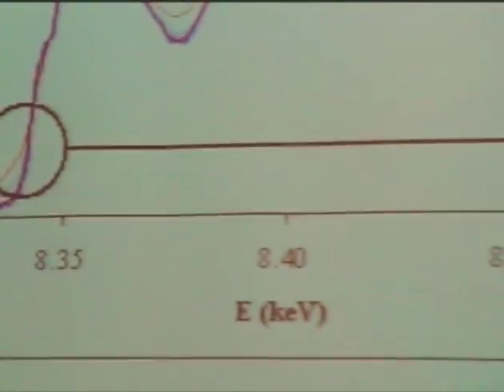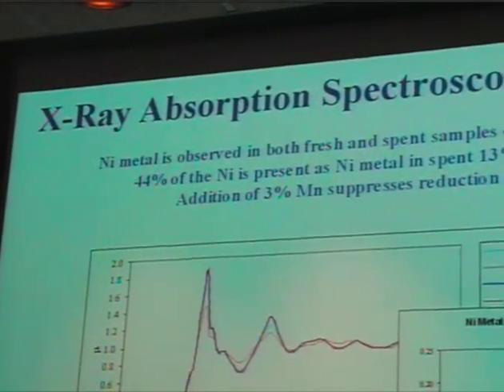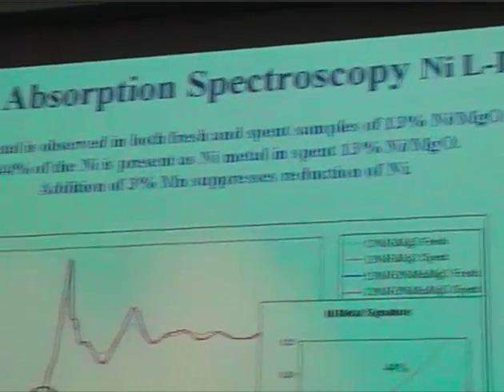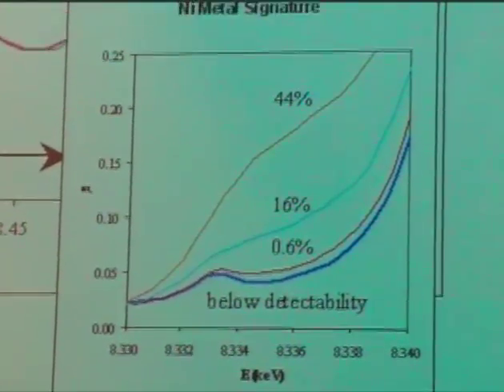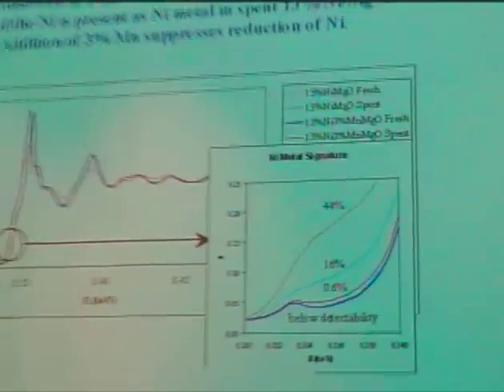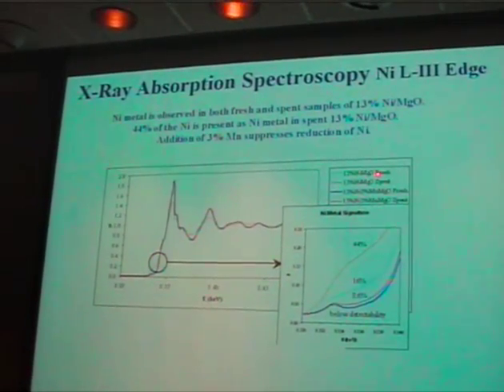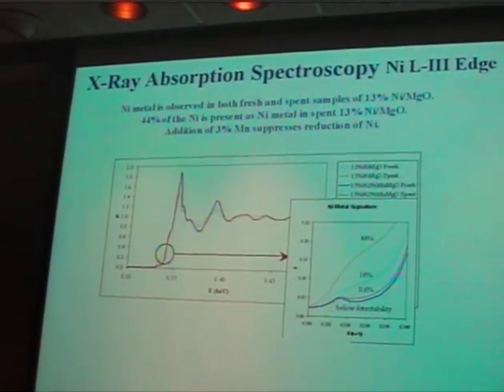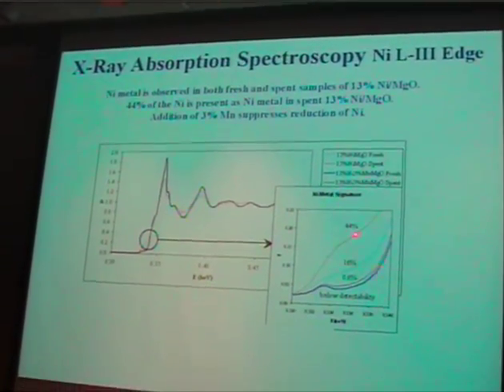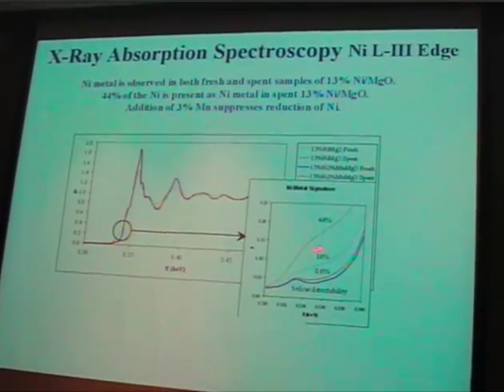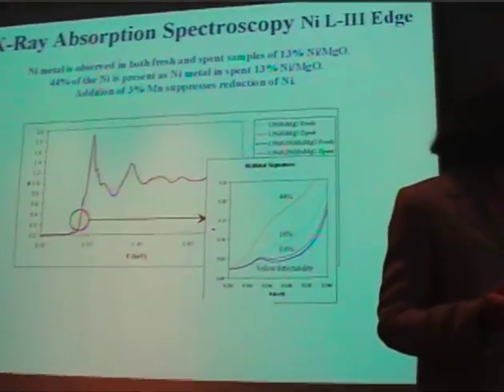So here you can see the blue line would be the fresh catalyst with manganese. We're seeing no detectable nickel metal. And then with use, about 0.6% of the nickel gets reduced. Whereas the fresh catalyst without the manganese, you're going in with already 16% nickel metal, which you saw in the TEM. And then after use, and we're talking about a day of catalytic use, you're already having 44% of the nickel reduced. So this gave us instructive information.